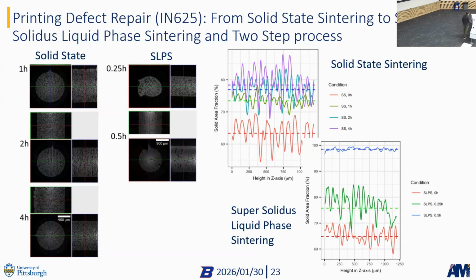So that's a really cool thing because now we basically have a mechanism to repair large defects, right, without distorting the part. Because now we need to be very careful. If we go into liquid phase sintering, we just have a blob afterwards, right? It doesn't matter what you print. It's literally just a drop, right? We did this many times when we went a little bit too high. But yeah, be careful, find the right temperature, and you can actually repair defects in your printed structures.